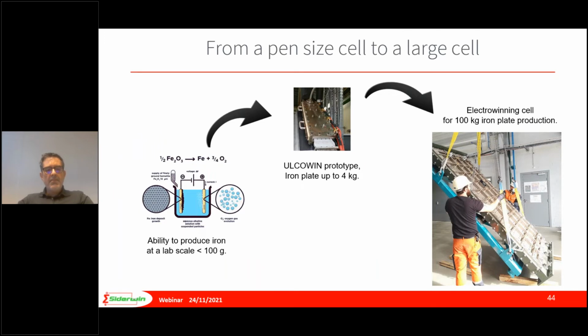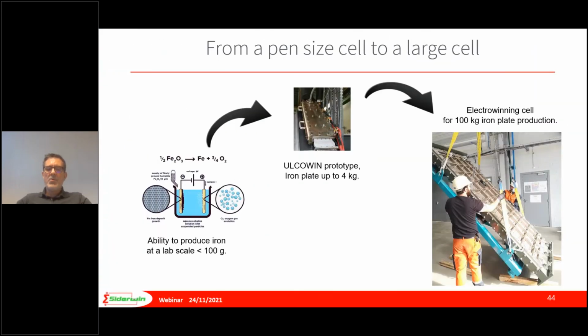As you can see here, in a lab experiment we are of course able to produce iron at a lab scale below 100 grams. During the Ulcowin project with the prototype, they were able to create an iron plate of up to 4 kilograms. And then, as you can see on the right, the idea was to build a pilot cell to generate an iron plate of 100 kilograms. So one of the important parts of the project was to achieve this pilot cell, able to generate such an iron plate of 100 kilograms.